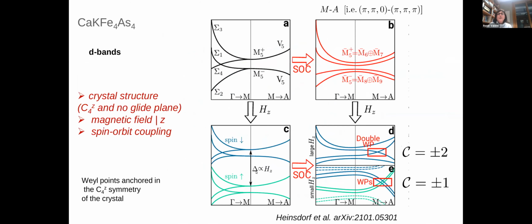Mm-hmm. Okay, so the order of the Zeeman splitting, in principle, if I want to get this double Weyl point, is rather large. So it means I have to apply rather strong magnetic fields. So that's why what we did is we extracted the order of magnitude from the polarization of the magnetic moment. So we need to polarize them along the z direction with a magnetic moment of 0.6 mu Bohr.